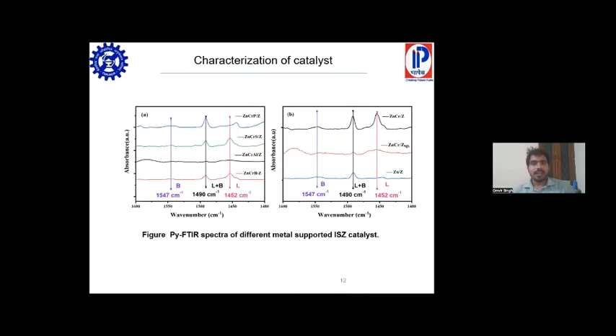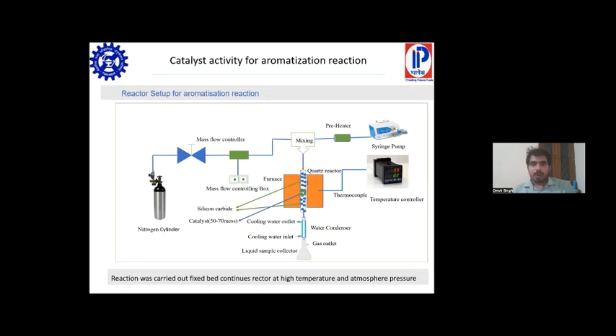the reaction. Then come to pyridine IR to distinguish which acidic sites are present in the catalyst. After the loading of a different metal, the Lewis acidity is increased, which corresponds to 1452 centimeter inverse. The peak intensity of the Lewis site is increased as compared to Brønsted due to the increase in Lewis acidity in the material after the loading of a different metal.